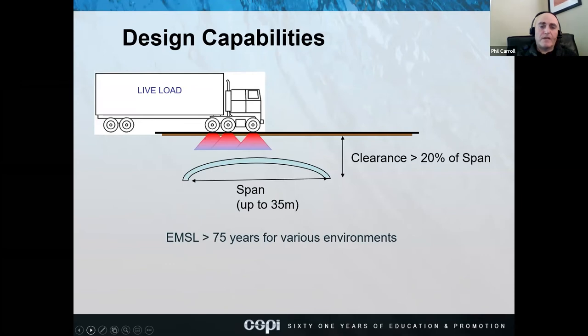So, design capabilities for these, especially deep corrugated structures: they can go all the way up to 35 meters in span, and the clearance has to be greater than 20% of the span. So that's the vertical clearance. And you can get an estimated service life greater than 75 years. Here in BC, where I'm from, commonly the DOT requires a service life of 100 years. So we just run the equations a little bit further into the future.